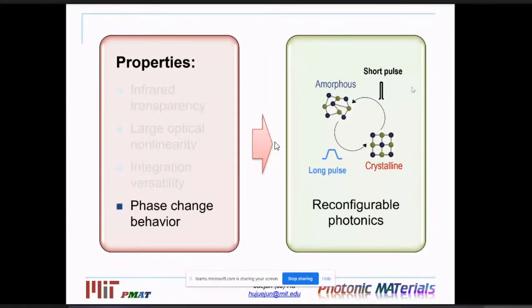But you really have to go up to pretty high temperature to change the dynamics, because the temperatures we're talking about here are at least 300 degrees Celsius for crystallization and 600 degrees Celsius for melting. So room temperature fluctuation is not a big deal. But if you're trying to use it in a high temperature environment, like 100 degrees Celsius, you have to take that into account. Or it could be under some specific light. You are exactly right. If you use a laser with very high power, then you have to take that into account. Yeah, thank you.